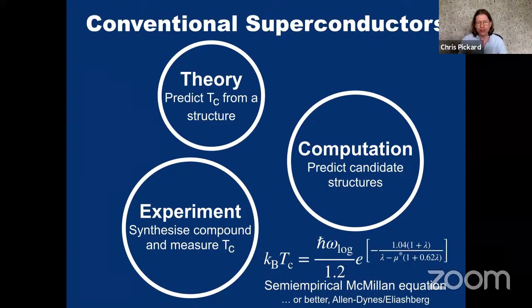So roughly, what do these expressions for TC look like? Well, I put at the bottom of the slide the semi-empirical McMillan equation. This depends on some parameters that can be computed, such as lambda, the electron-phonon coupling, and the average of the frequencies of the modes, and also parameters such as the Coulomb screening, the mu star, which is a slightly free parameter that tends to be around 0.1, that you can tweak around a little bit.